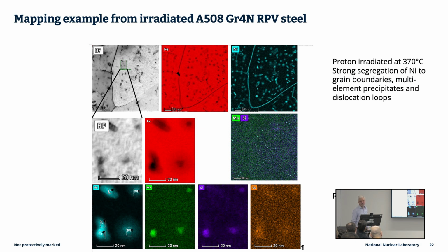This is another EDX example from Alex's work on irradiated pressure vessel steels. So this one was proton irradiated at DCF, and then has been analysed in the Talos microscope here. In a completely different ferritic steel, we've got segregation of nickel to the grain boundaries, really nicely illustrated here. And you can see this section of the grain boundary is really quite well aligned, and it gets much broader here as it goes around the corner.